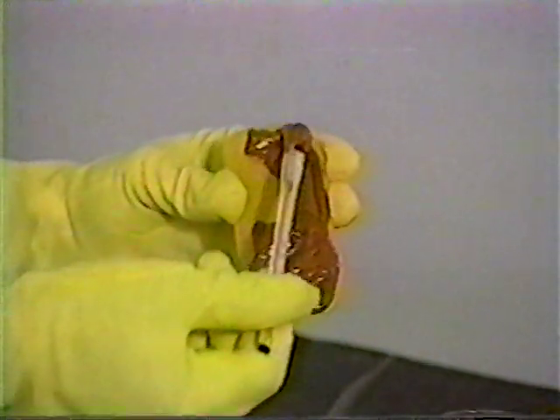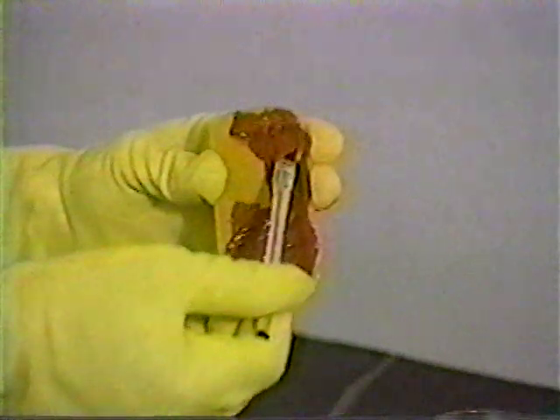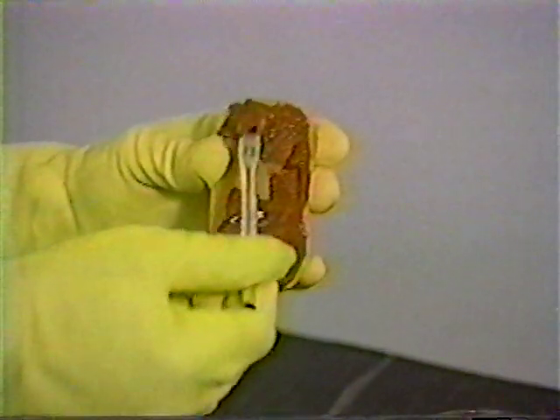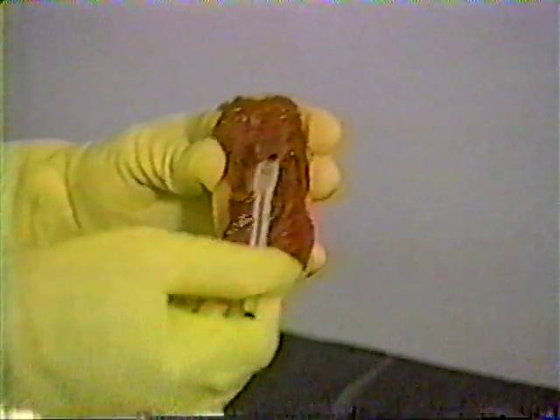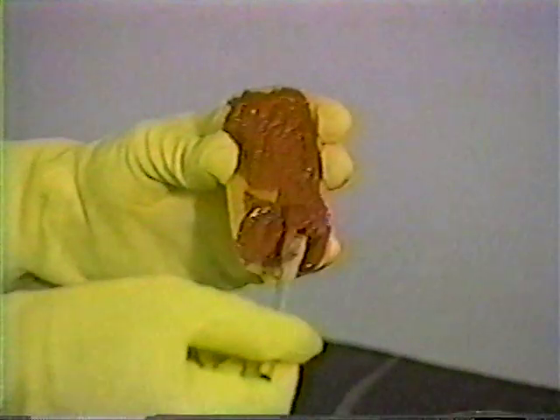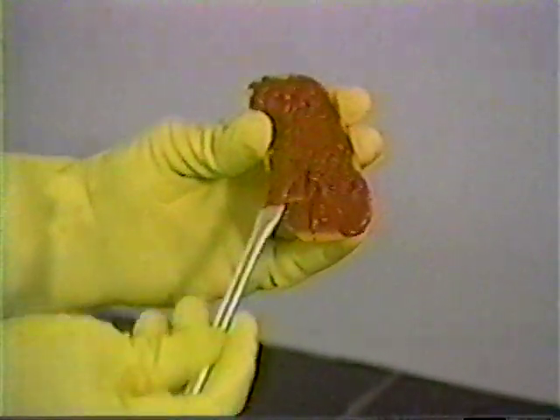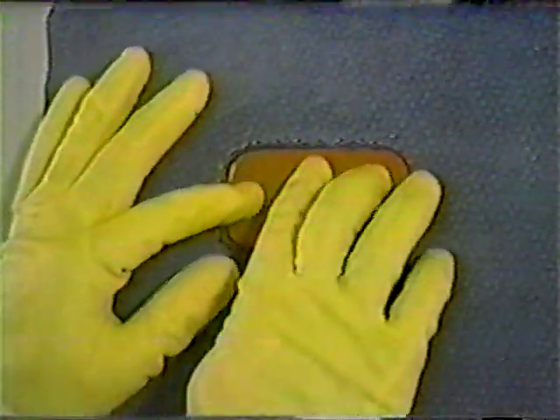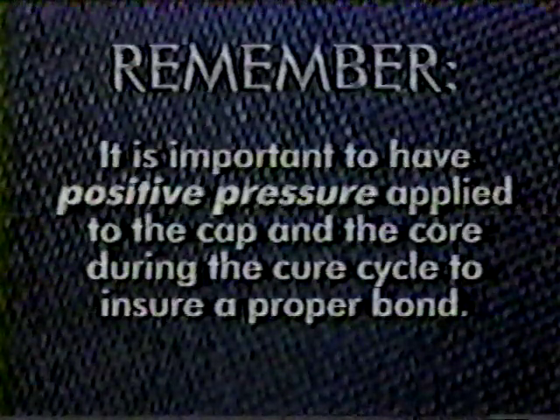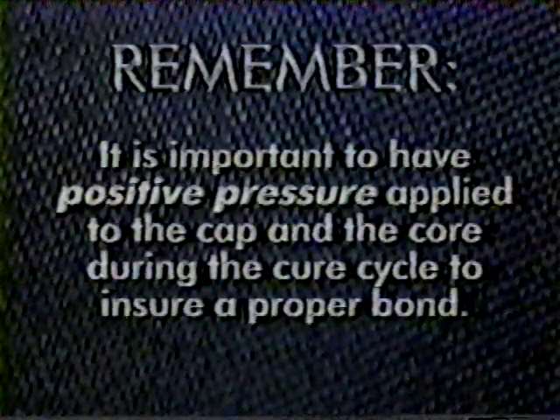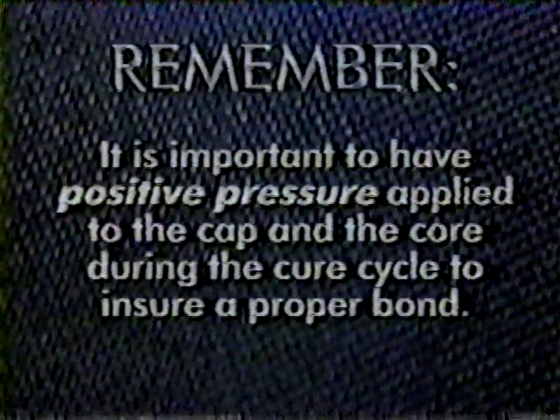Next, coat the exposed surface of the cap with enough adhesive to bond it to the honeycomb, making certain the adhesive is not being applied to the peel ply surface. Then, place the cap firmly on the repair area. It is important to have positive pressure applied to the cap and the core during the cure cycle to ensure a proper bond.